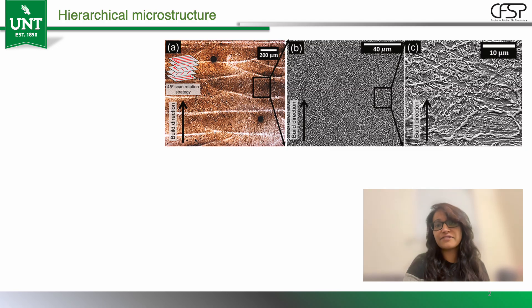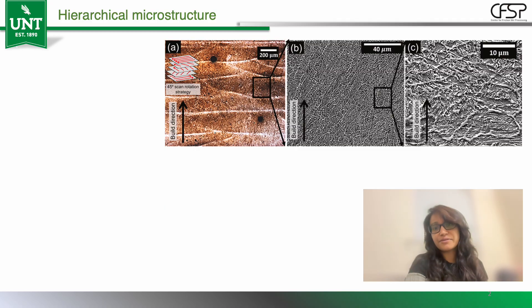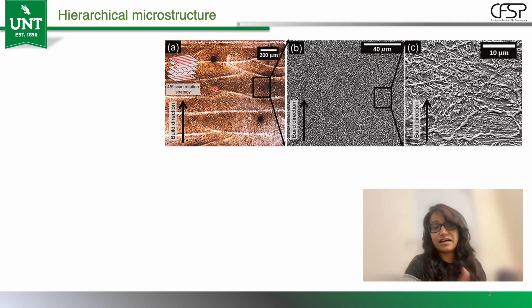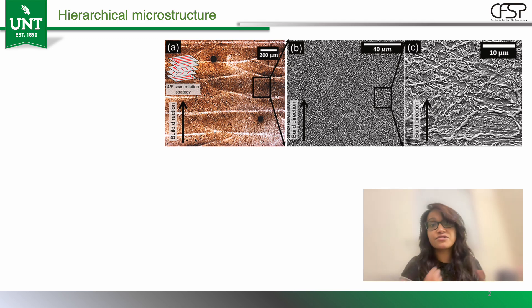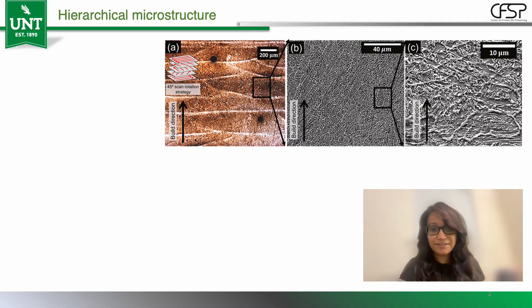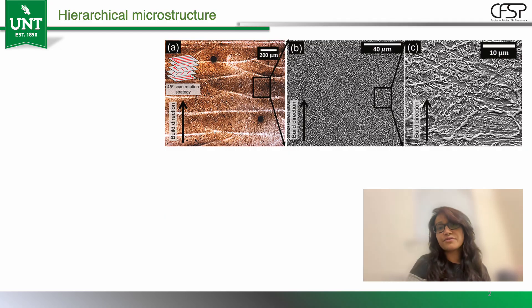I want to show you how the microstructure of a DED-printed steel looks at various length scales. When the laser melts the powder and it solidifies, a new layer is added on top, so the material experiences multiple thermal histories. At macro length scale, as you can see in this image, residual stresses arise between the layers. At micro scale, dendritic structures form inside each melt pool, leading to another set of residual stresses. And at nano scale, tiny segregations and dislocations contribute to stresses at nano scale. A single printed block of steel contains a whole hierarchy of stresses, all interacting with each other.